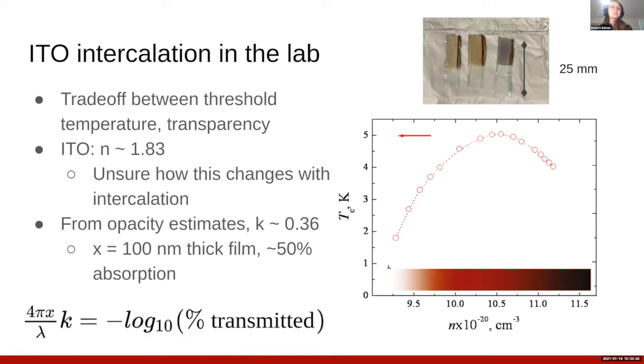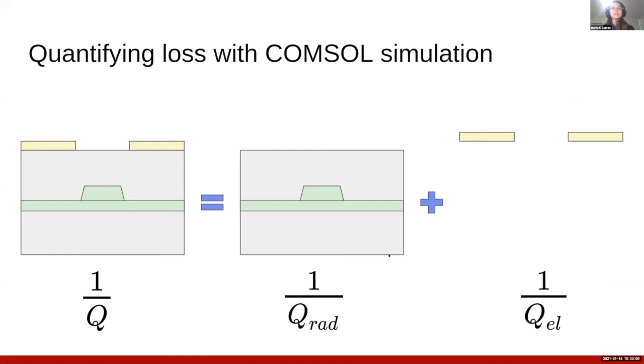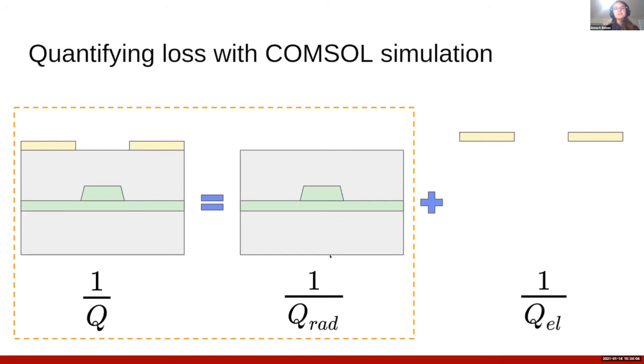For ITO, the refractive index is about 1.83. I don't know how this changes with intercalation. And we've estimated from old samples from our lab that the extinction coefficient is about 0.36 based on this equation at the bottom. Now, we can quantify this loss using a Comsol simulation since we have all this refractive index information. If we assume that the electrodes are just a small perturbation to the system, then we can do a Comsol simulation of the full system and the system without the electrodes and compute the quality factors of both of those in order to extract the quality factor of the electrodes alone.